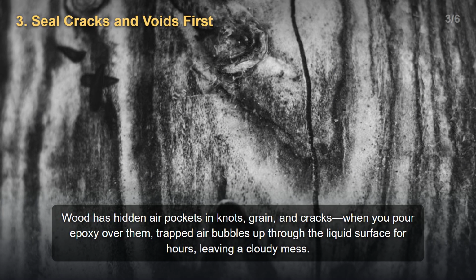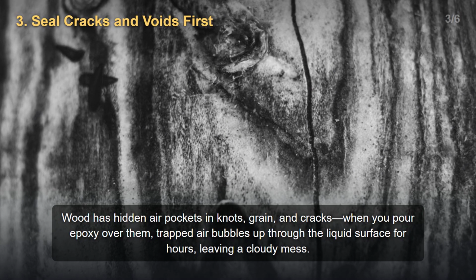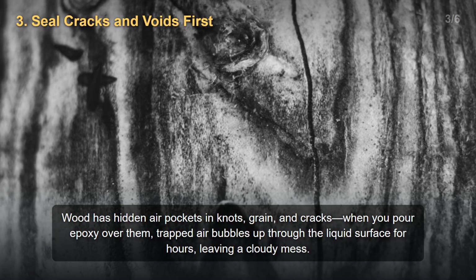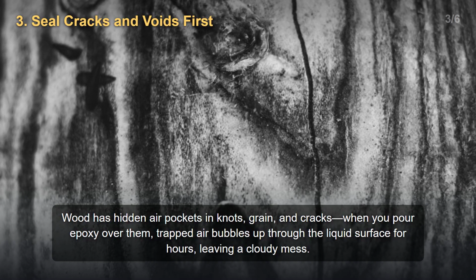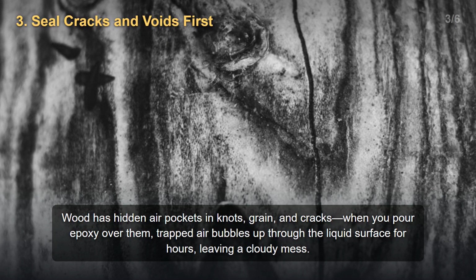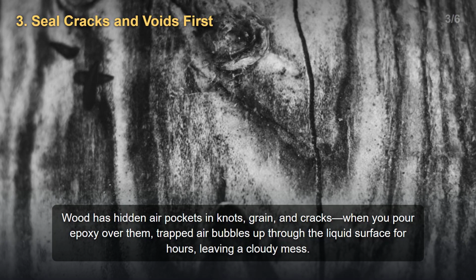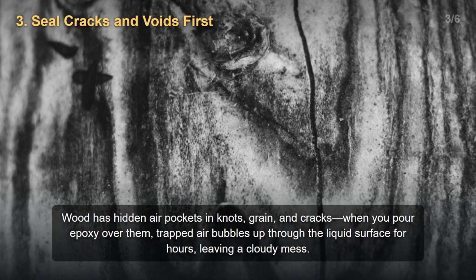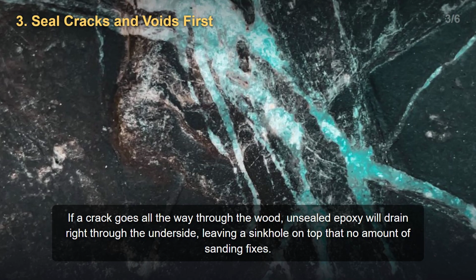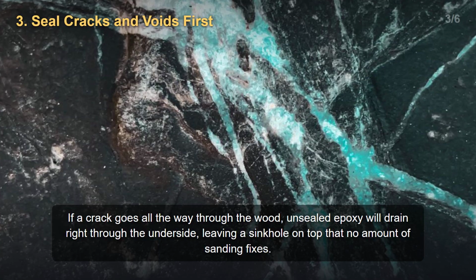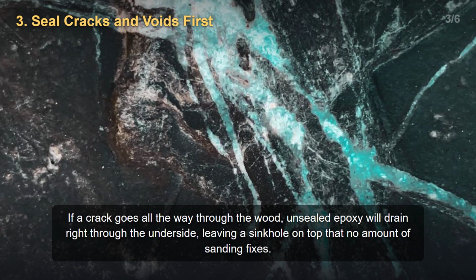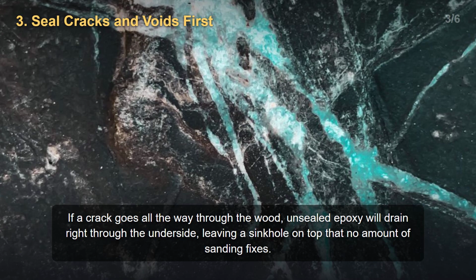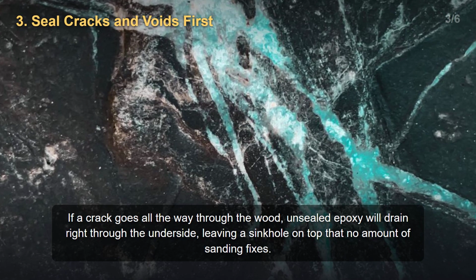Seal cracks and voids first. Wood has hidden air pockets in knots, grain, and cracks. When you pour epoxy over them, trapped air bubbles up through the liquid surface for hours, leaving a cloudy mess. If a crack goes all the way through the wood, unsealed epoxy will drain right through the underside, leaving a sinkhole on top that no amount of sanding fixes.